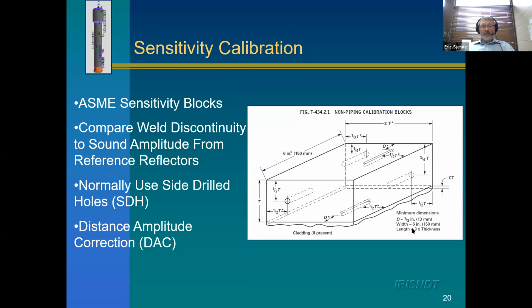So we're allowing defects or discontinuities to stay in the material that are fine, and we're making sure the customer knows when there's repairs and it's not safe to operate that vessel. And that's what this calibration is. And it uses a block called an ASME block. And that's part of the code. It's described in the code. And that just allows us to set the amount of sound pressure, the y-axis of that graph I showed you. So we can do a proper inspection and we know what sensitivity we have.